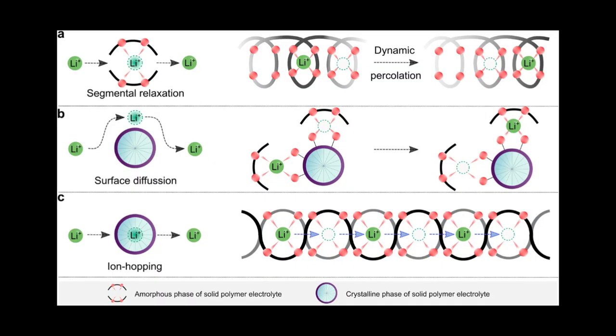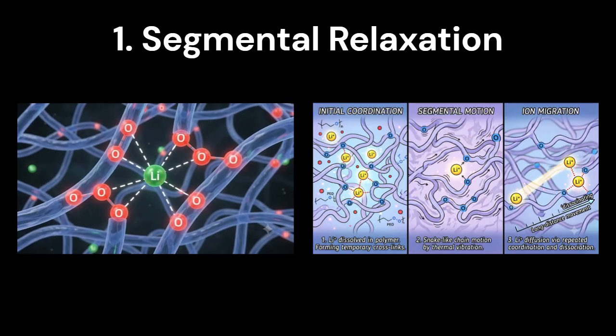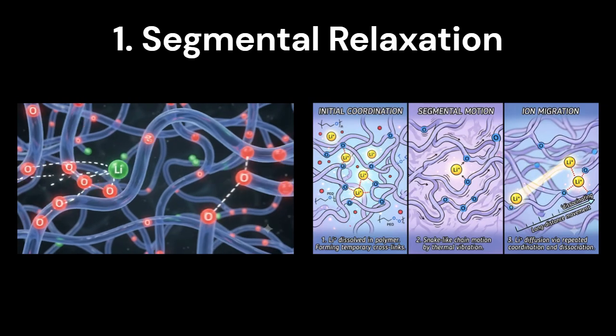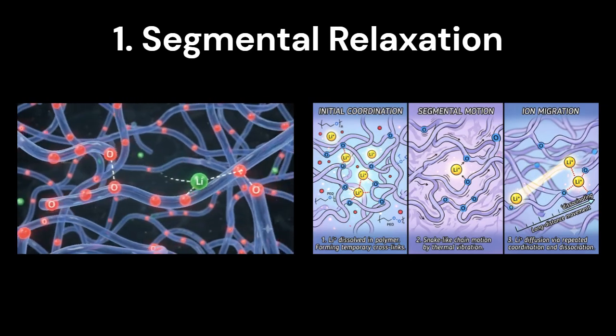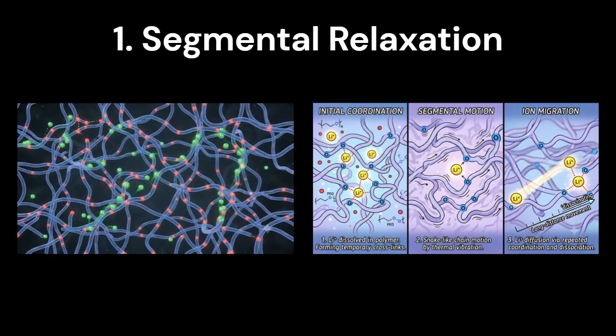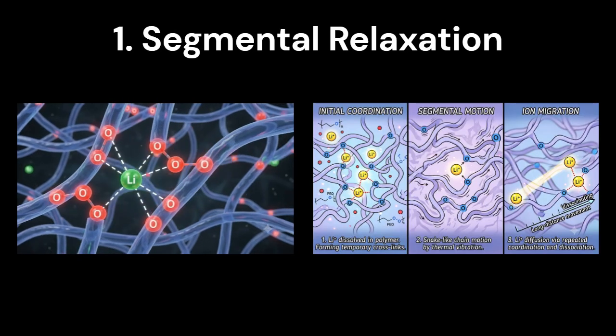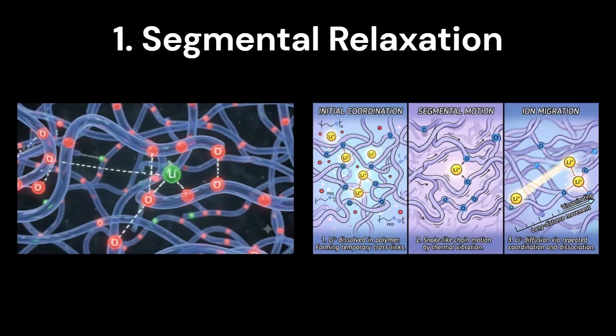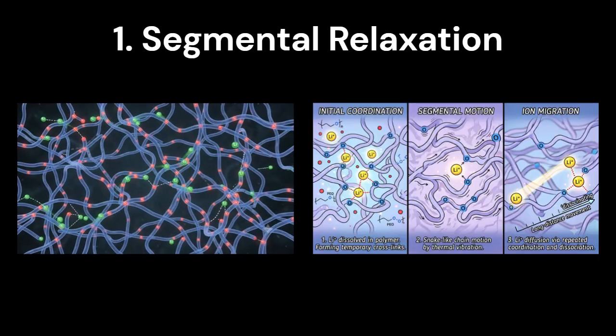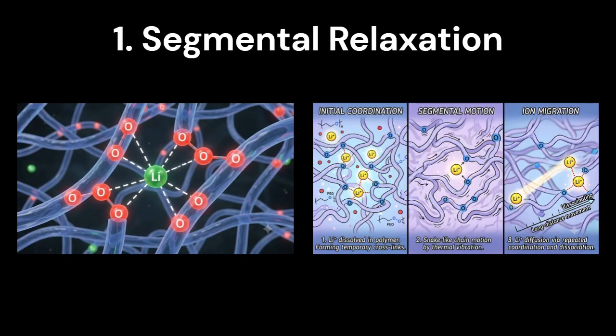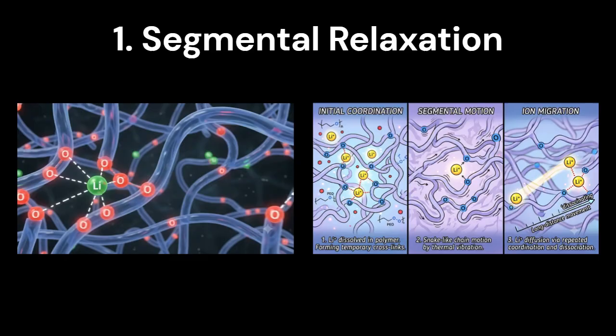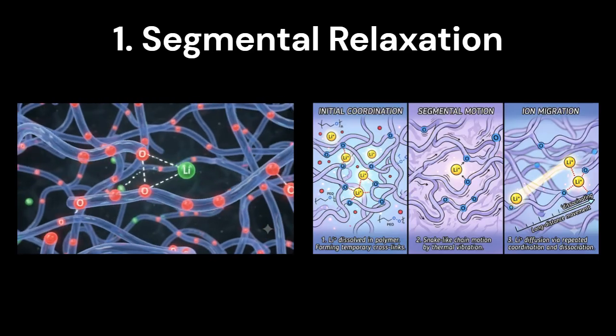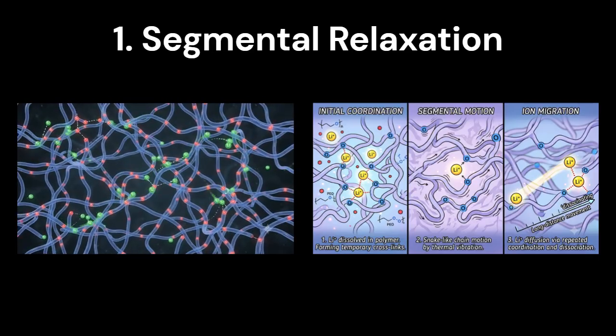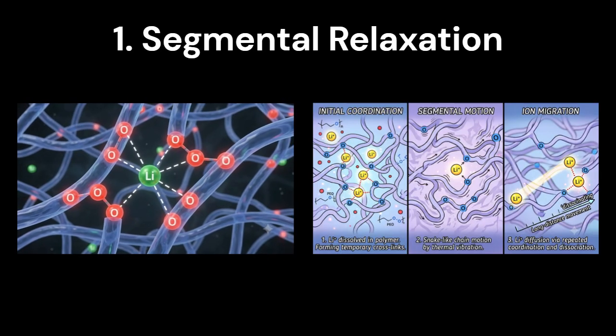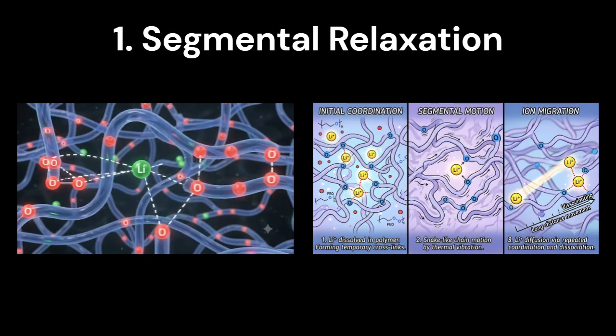Ion conduction in polymers mainly occurs through three mechanisms. First, when lithium salt dissolves in the polymer, lithium ions coordinate with polar groups such as ether-oxygen, forming temporary cross-links between chains. The polymer segments then undergo snake-like motion by thermal vibration, allowing the ions to repeatedly coordinate and dissociate as they move over long distances. This process is called segmental motion and mainly takes place in amorphous phases.